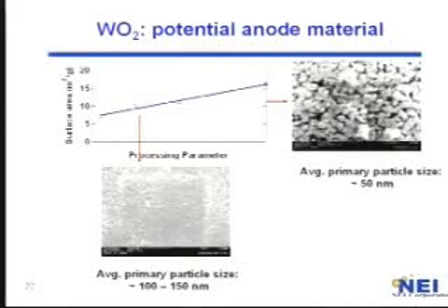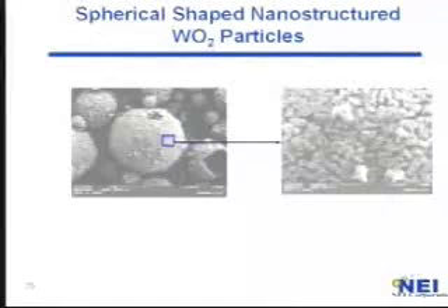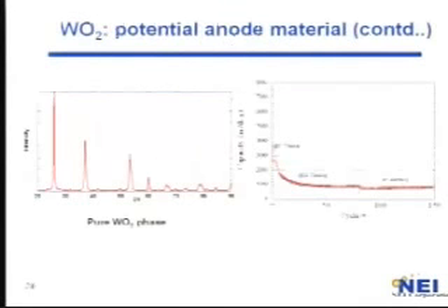Again, just to show what we can do, how the synthesis of the material can achieve different particle sizes and performance of the material. Here, by controlling the processing parameters, we're able to control the primary particle size, going from 100 to 150 nanometer to 50 nanometer. What you really want in a nanomaterial, because ultimately these materials have to be packed in batteries, is a nice spherical morphology so that you can have a very high packing density and a high volumetric energy density.